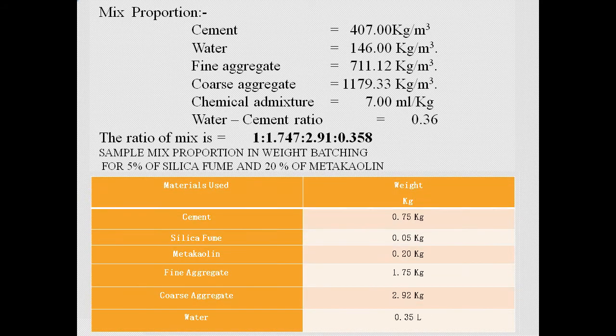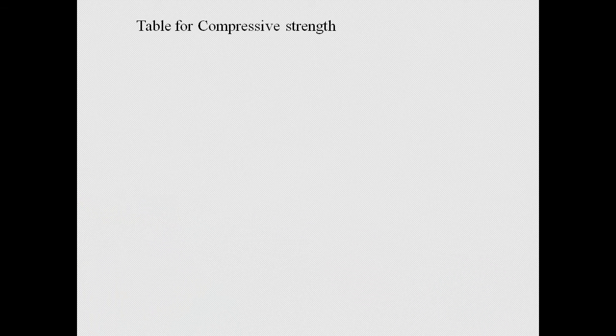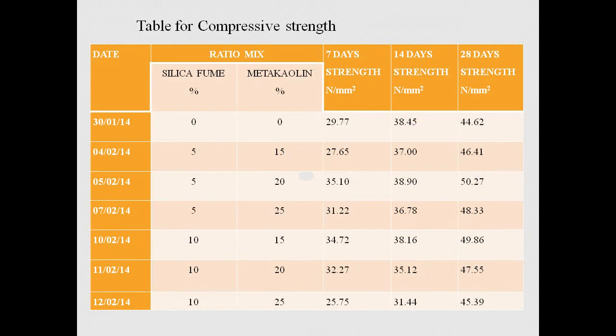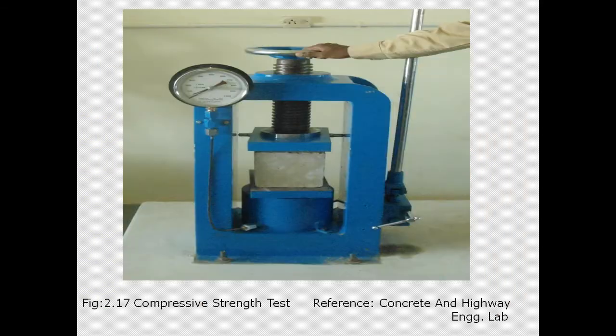And this is the sample calculation for 5% of silica fume and 20% of metakaolin replacement. And this table explains the 5% replacement with 20%. This is the table for compressive strength. The maximum is obtained at 5-20 replacement, that is the 5th mix, the ratio of silica fume 5% and metakaolin 20%, which yields the maximum 28-day strength of 50.27.